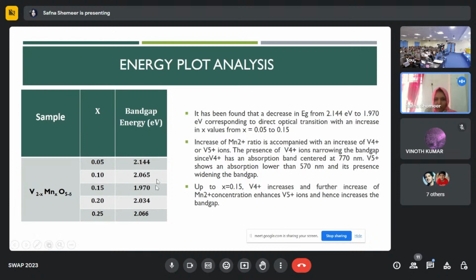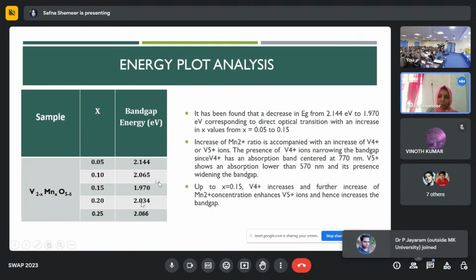So up to x equal to 0.15, V4+ increases, and further increasing manganese concentration enhances V5+ ions, and hence increases the bandgap. And this is the SEM and EDS of the samples, and it shows the highly dense growth of large crystallites with irregular shape and size, with non-uniform distribution of particles in the micron region.